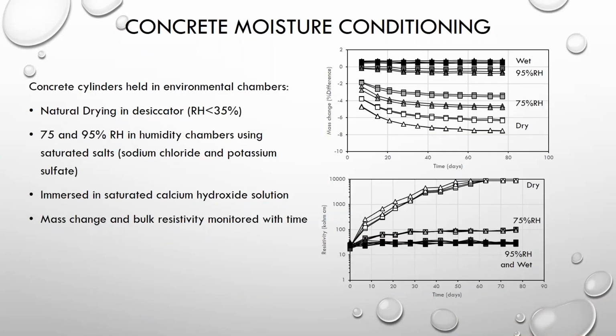The concrete cylinders were conditioned with the moisture content. One set was dry, which was left below 35% relative humidity. And then we had, as previously mentioned, 75 and 95 relative humidity using sodium chloride and potassium sulfate. Then there's an immersed, which was soaked in calcium hydroxide solution. The mass change and bulk resistivity were monitored over time, as you can see over here on the right.